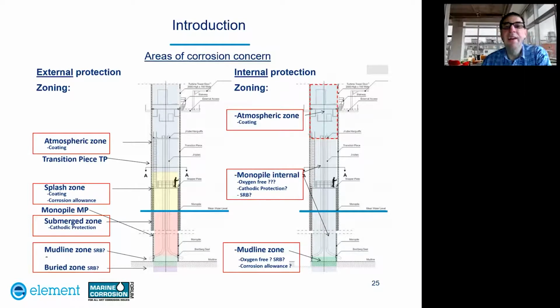If we then look at the internal surfaces of the structure, in the upper reaches you can get some condensation of seawater, so you need to protect these surfaces with coatings. Then if we move down to the internal surfaces of the monopile, these would typically be flooded with seawater, so they would be protected using coatings and cathodic protection. They can also be subjected to sulfate reducing bacteria activity. So this is a potential risk in these regions, that you get this microbial corrosion occurring, and this can also occur down below the seawater in the mudline zone.